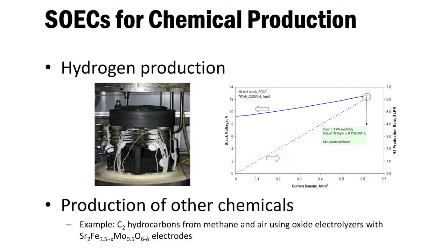So here is an example of hydrogen production that I worked on years back. This shows a 10-cell stack operated at 800 degrees C, with an input of about 1.1 kilowatt, producing about 3 something standard liters per minute of hydrogen, with about 54% water utilization.